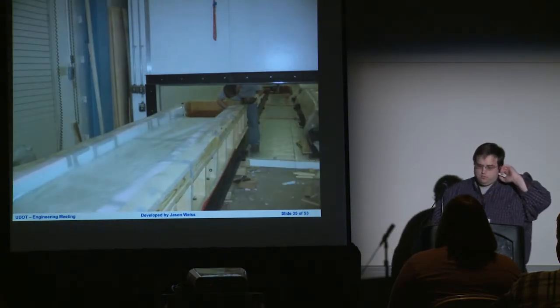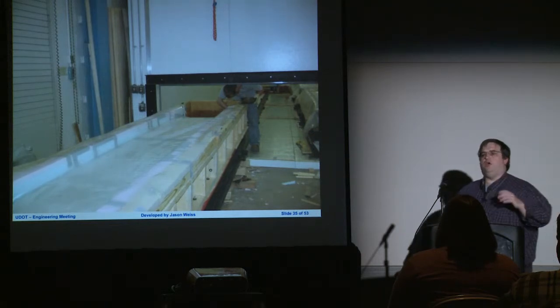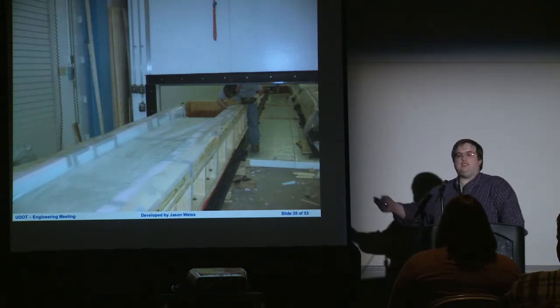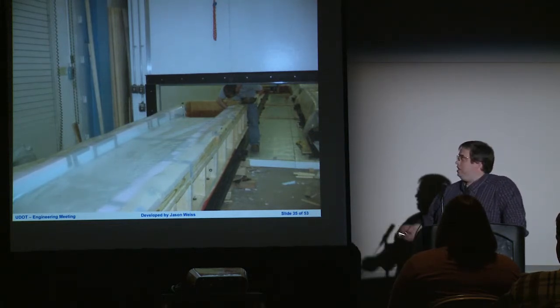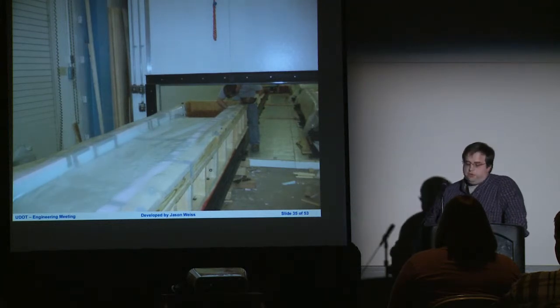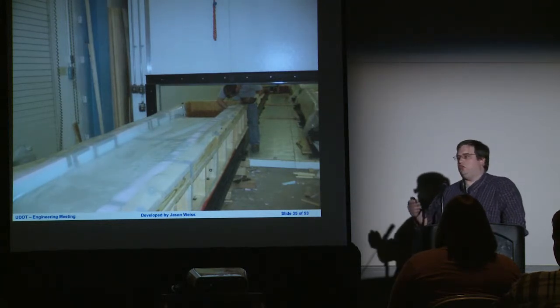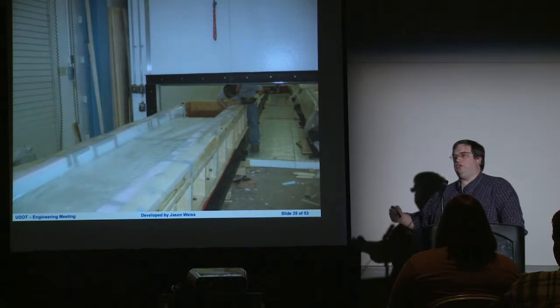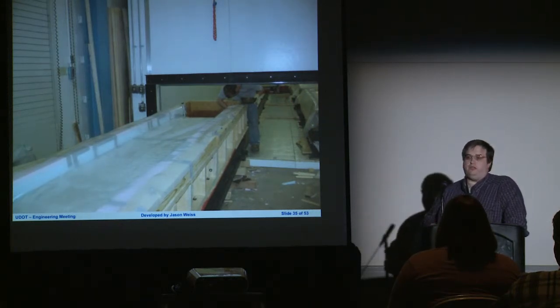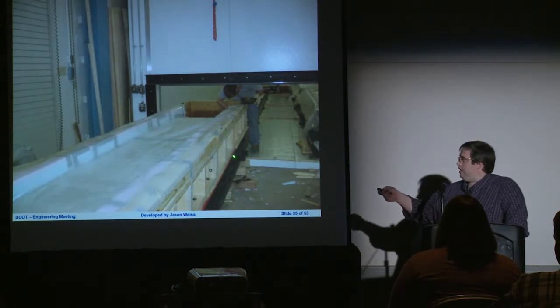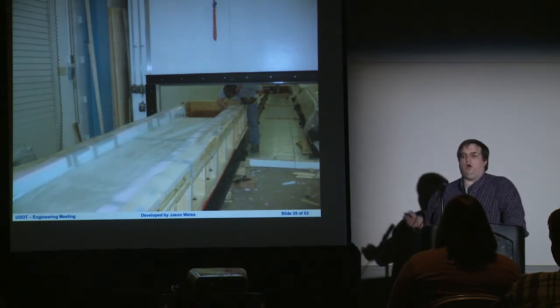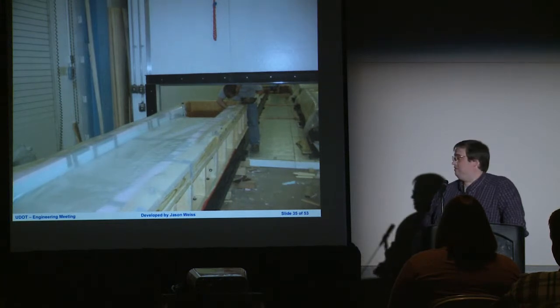Now, in addition to doing these small rings, we've said, well, let's see if we can do this on larger sections. There's a room that's set up at Purdue where we essentially have the ability to control temperature, moisture, and wind speed. We can do this on samples that are up to 35 feet long. In this case, we're actually doing this on bridge deck sections, where they're essentially 3 feet wide and about 15 to 16 feet long.